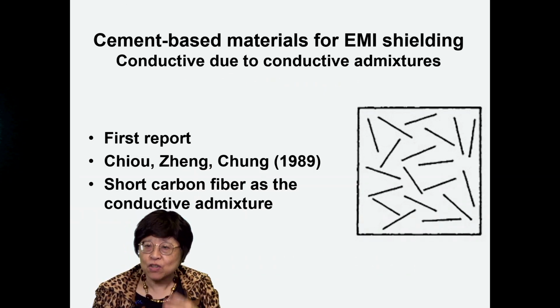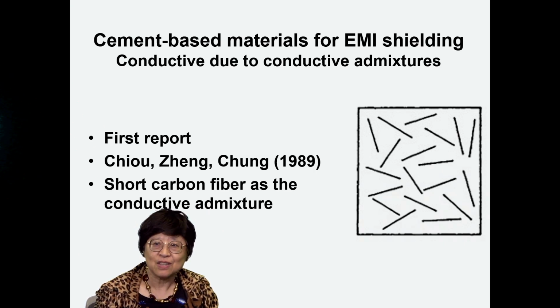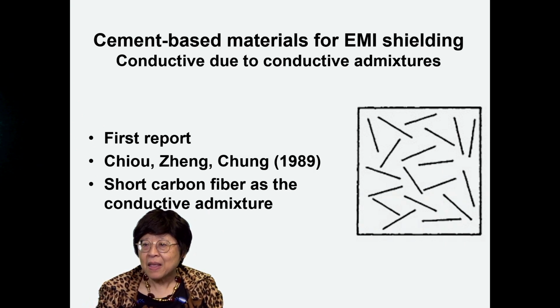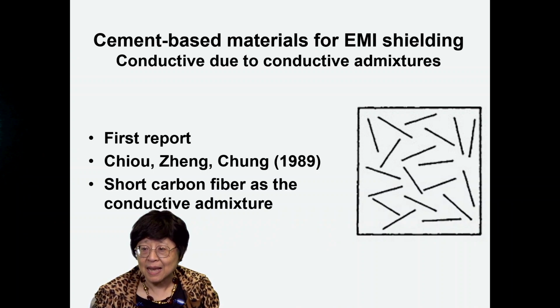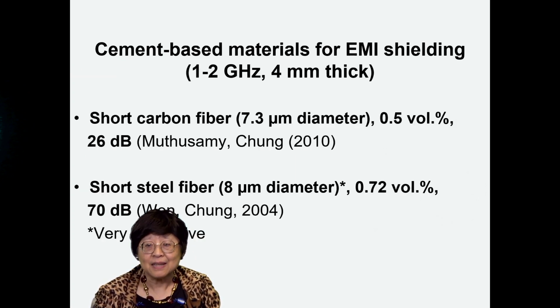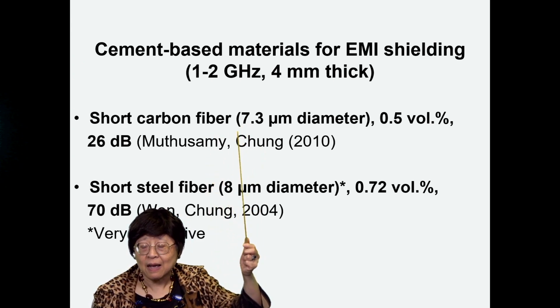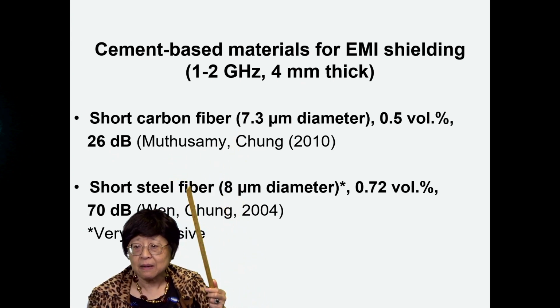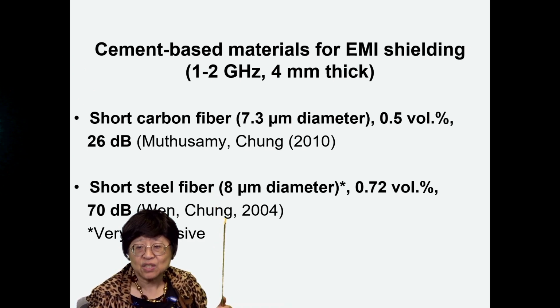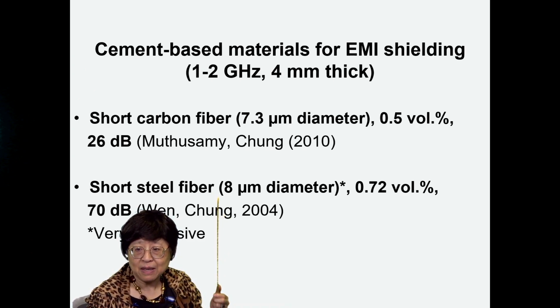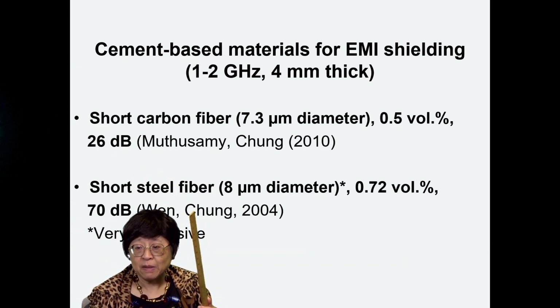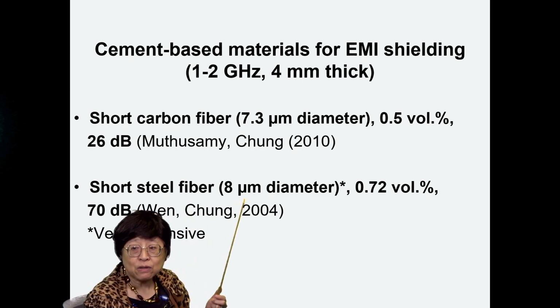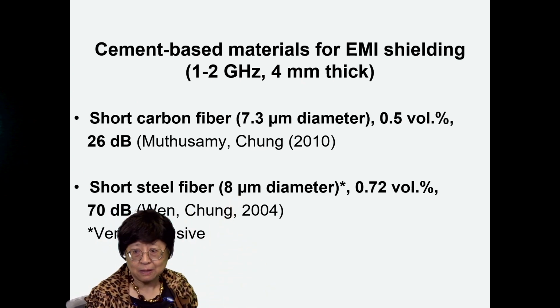While cement-based materials for shielding are conductive due to the conductive admixtures, that is, the additives that you throw into the concrete mix. My students and I provided the first report of that back in 1989, and we put in short carbon fiber as the conductive admixture. After that, the technology has become better and better, and with the short carbon fiber, 7 micron diameter, we got 26 dB of shielding. With short steel fiber, 8 micron diameter, we get 70 dB, even higher, 70 dB as opposed to 26 dB. So steel fiber is even more effective than the carbon fiber. But this micron diameter steel fiber is extremely expensive.